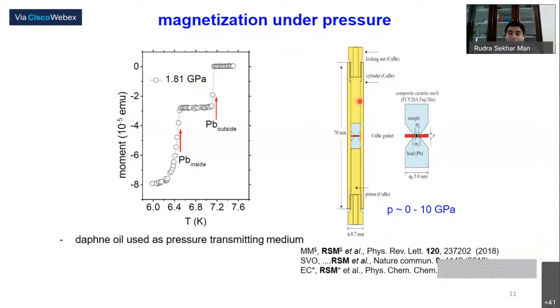That means you can put your sample inside a pressure cell. It depends what kind of sample you are interested in, in this case the lead, or you can have some other samples which are really pressure sensitive. Then you can tune how the magnetic interaction and all these things change, and the whole thing can be placed inside this SQUID magnetometer, and then you can also measure.